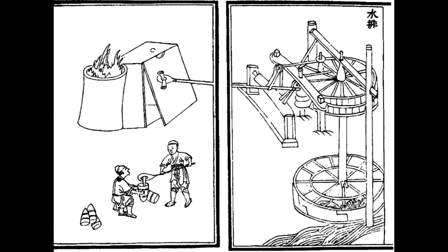But we're not done. The key technique that Chinese iron workers seem to have developed here is malleabilization. By heating the iron to melting temperatures, or just below, in an oxidizing environment, which is to say open to the air, the iron worker can cause a few things to happen. First, the oxidation process begins to draw off the carbon from the iron.